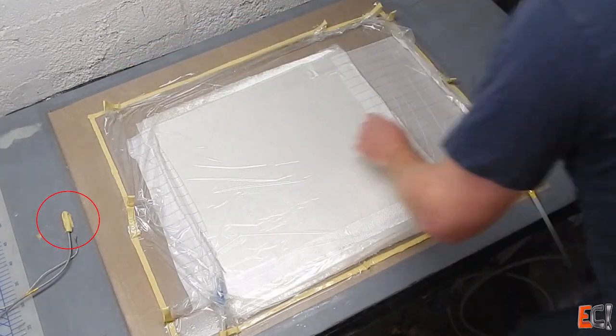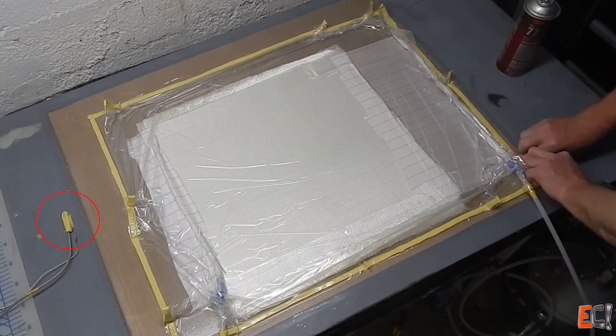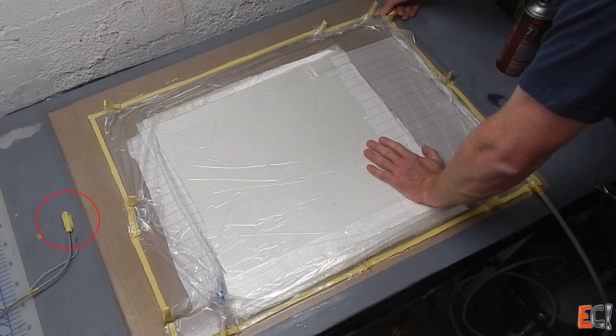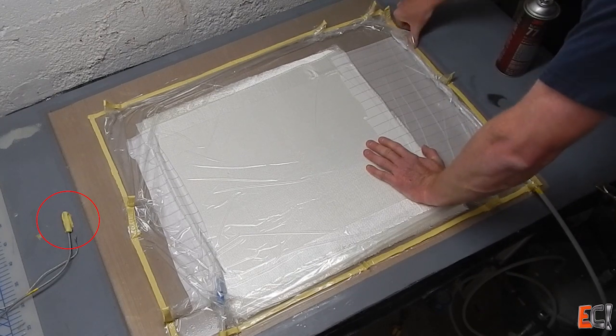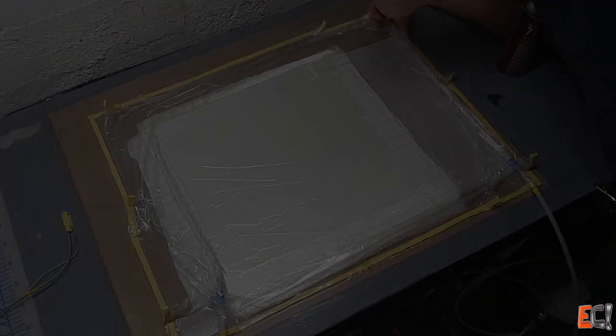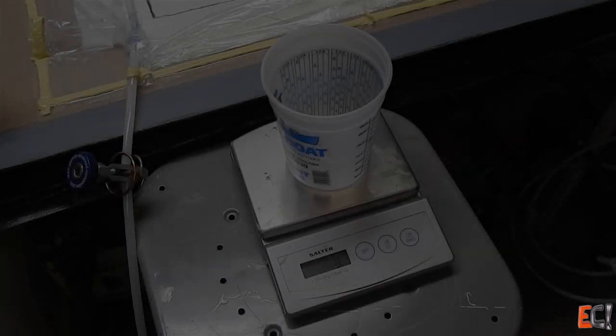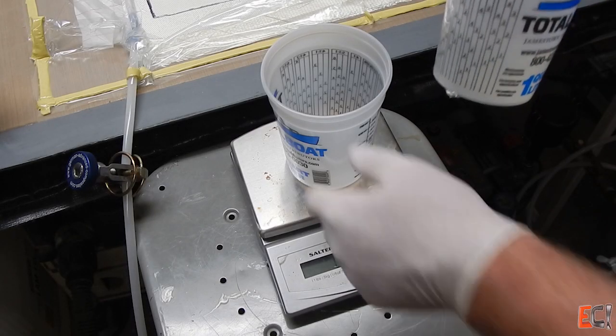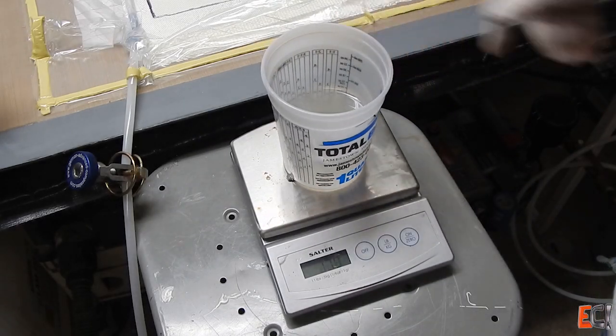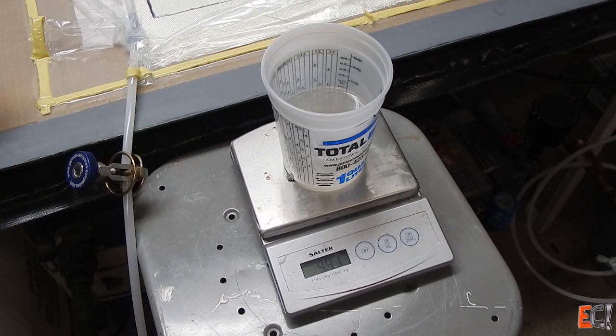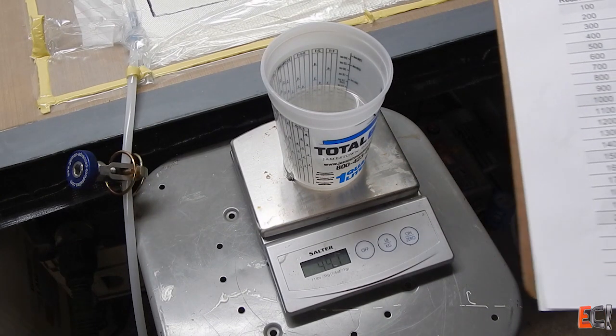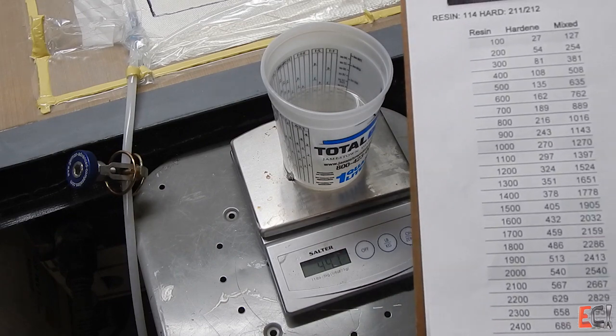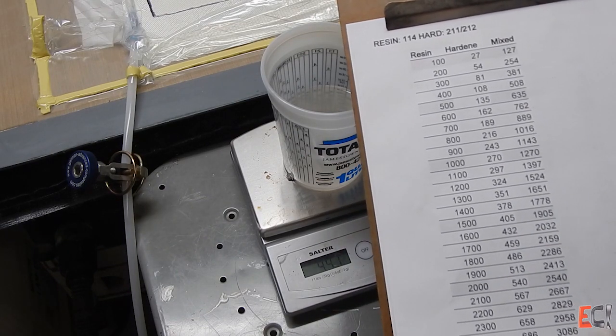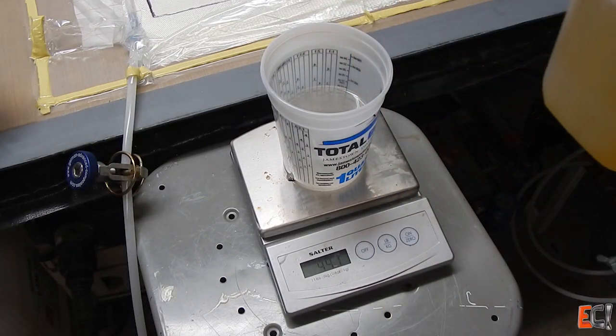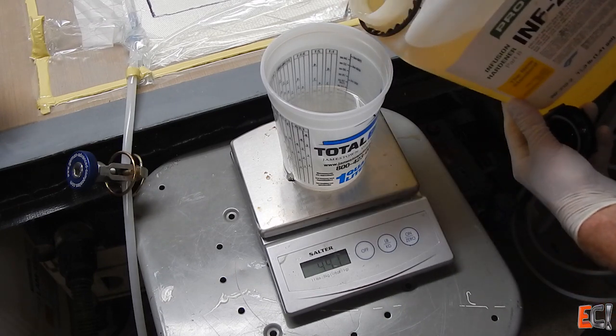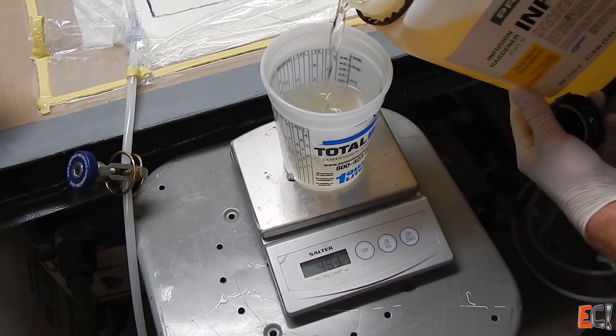You can see on the left my thermocouple for the temperature controlled table is stuck down with some tacky tape. This table is an aluminum honeycomb core with a heating mat underneath, which is great for infusion. And here I've tared the scale with an empty cup, come back with the amount of resin I've calculated I will need. This is a cheat sheet for this type of ProSet that calls out in 100 gram increments resin to hardener ratios and the total amount that you will need.